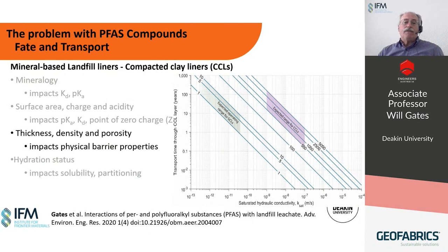Compacted clay liners should typically be a minimum of 600 millimeters thick, but the thickness only goes so far. Low saturated hydraulic conductivity is highly dependent on the compaction density and the low porosity that results from compaction, and thus that imparts a high degree of tortuosity on the liner system. Thus, the physical texture or microstructure of the liner is key to limiting the advective and diffusive transport of PFAS. In general, this will only serve to retard the migration of PFAS, but not stop it.